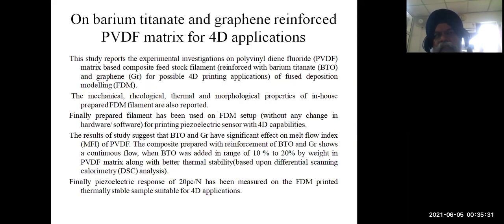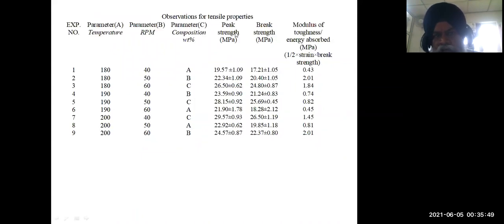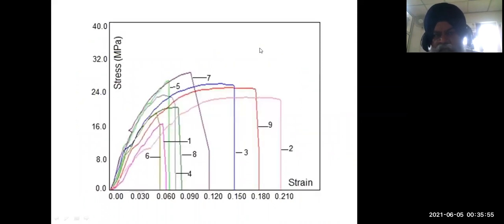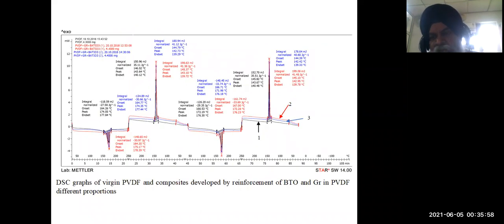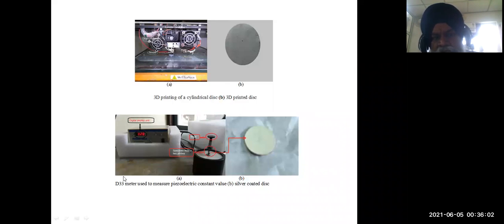So similarly, in another case, we use PVDF with the reinforcement of barium titanate and graphene to give some piezoelectric property. Here we are interested to use the voltage as a stimulus, not as a magnetic field stimulus, but the voltage as a stimulus. So again, we use PVDF with graphene, with barium titanate, and then playing with different proportions, we try to find out what is the peak strength, what is the break strength, what is the modulus of toughness, then the stress strain curve, their thermal analysis, whether it is thermally stable or not. And we try to find out d33. Basically, this is 20 picocoulomb per Newton. This we got out of this, right? So this is another important thing that we observed with the different reinforcement of the material.